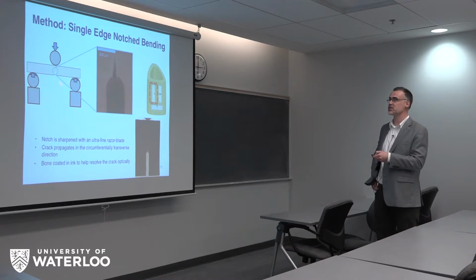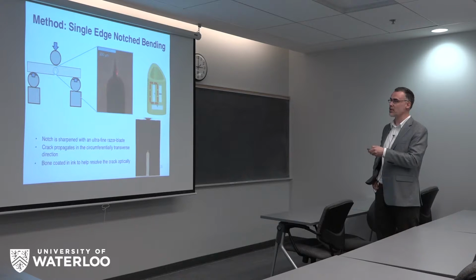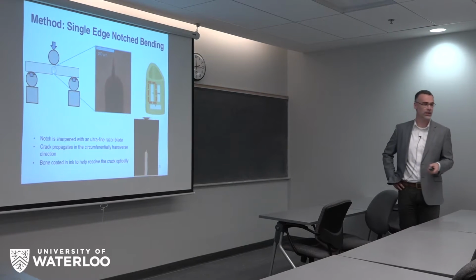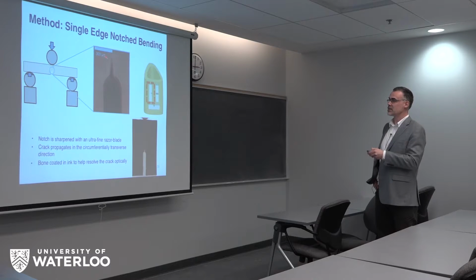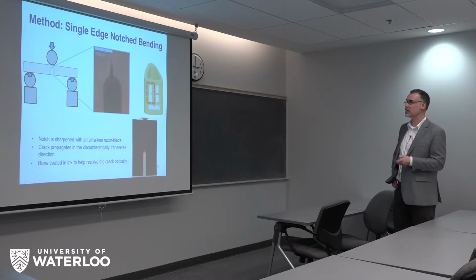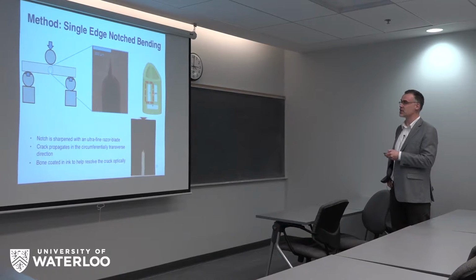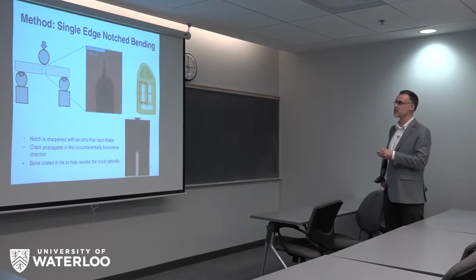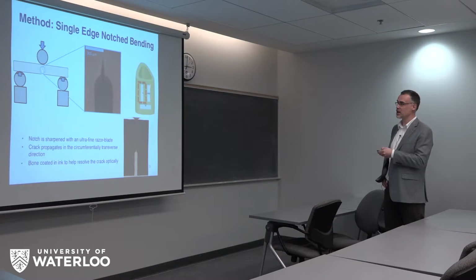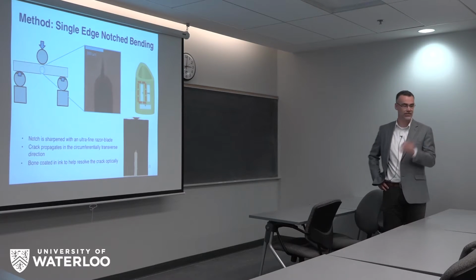We do this with a diamond wire saw, which is 300 microns in diameter. We end up with a semicircular end here, and then we sharpen it with a razor blade to get a very fine notch with the radius at the tip of around 5 microns, so it's very fine. And then we cut the specimen so that the crack is going to grow transverse across the bone direction, or across the long axis, which is most relevant to fracture, and then also in the circumferential direction. And that's mainly because if you try to grow the cracks in the radial direction, they deflect drastically, and it's very hard to do the testing.